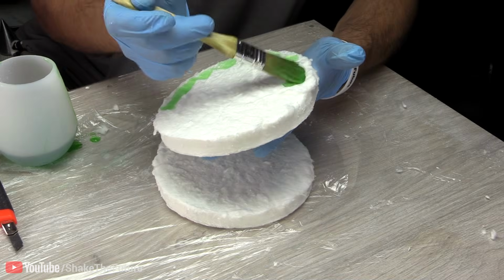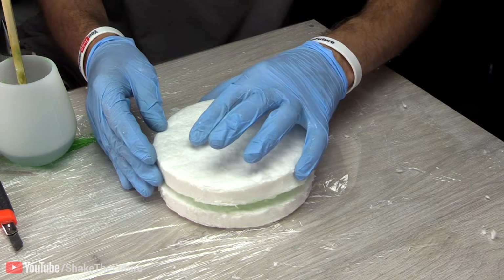So why did we sand the popcorn pattern, and why did I say that it's better not to put any water glass between ceramic fiber sheets? Well, it's to prevent the water glass from heating up on its own and to avoid possible microwave arcing. Just like with a glass plate, the water glass can heat up on its own and damage your kiln.